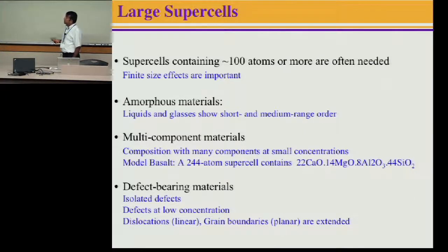So for example, in the case of amorphous materials like liquids and glasses, they do have this short and medium range order, which could easily be 10 angstrom or so. So in order to capture that, you might need to go beyond a 100 atom supercell.